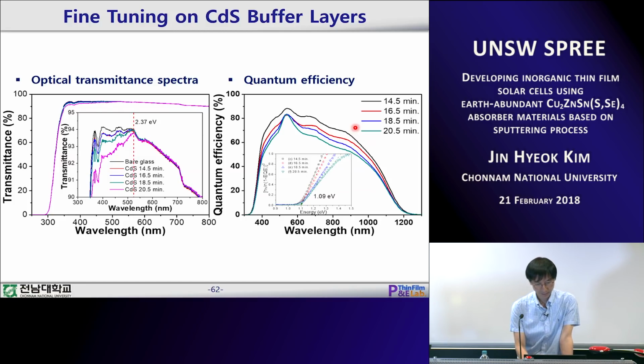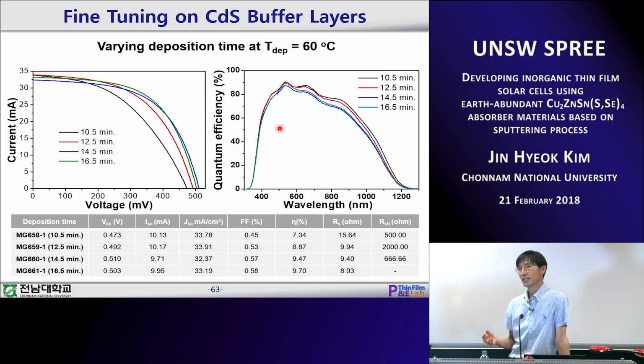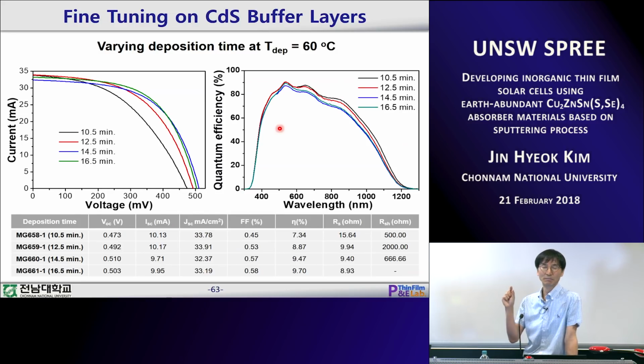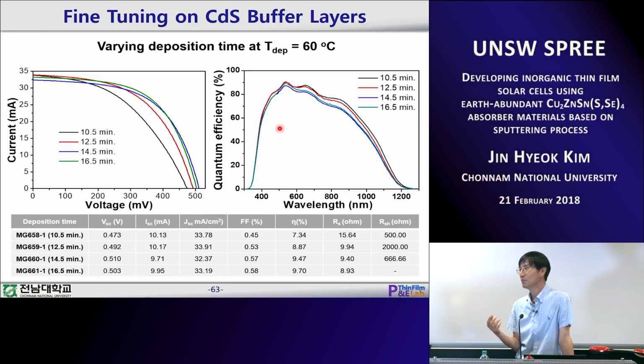But there are some things that we have to think about, JSC and VOC together. If we decrease the buffer layer thickness, we lose VOC, even though we could improve JSC. So so far we believe that there is a certain optimal thickness of the buffer layer. I would say it is around 30 to 35 nanometers. So we have to do more fine tuning on this buffer layer to get reasonably good VOC and reasonably good JSC.